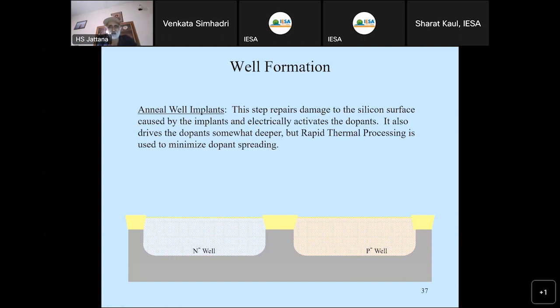So now after these wells are formed, annealing is done, and there is a rapid thermal process also. Basically, when we do the implant, if this is the surface and I am doing an implant here, the boron will sit just below the surface. It will not go deep inside the crystalline structure. And for that, there is an anneal step or drive-in step, which is at a high temperature. For say 20 minutes, 30 minutes at some 800 degrees centigrade or like that, then you get a proper profile. And while doing the implant, the top surface of the wafer, because implant basically is a collision. There are boron atoms, phosphorus or arsenic atoms which are directly hitting the surface of the silicon. And silicon is a crystalline structure, so it distorts the surface. And annealing, again, some of the crystalline structure which is distorted, by annealing it regains that.